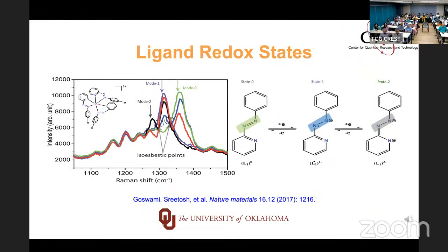The most important thing is that the azo group has three charge states: state zero, state one, and state two. This corresponds to the actual N double bond N versus its reduced forms. Essentially, as I take an electron out of this, you get this. Then I take another electron out, I get this. So these are states zero, one, and two. And they have beautiful Raman spectra exactly corresponding to those states. So by measuring the Raman spectrum, I can tell very accurately what state the molecules are in. This is something very unique to this organic system. Very few people have such an organic system where they know what the mechanism is. And here we see it.